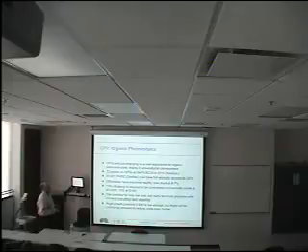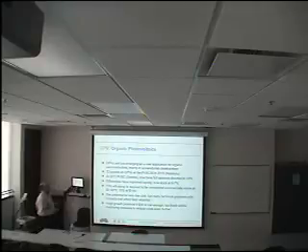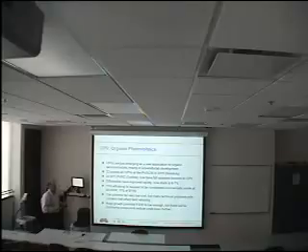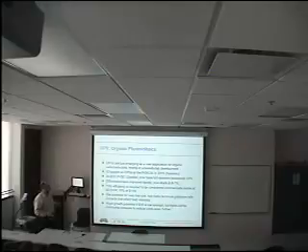Efficiencies have improved rapidly, though right now they're stuck around 6 or 7%. You need at least 10% efficiency to be commercially viable, and that's why they haven't taken off yet, at a cost of $0.50 per watt. If you could get the efficiency up to 15%, then the dollar per watt target is viable. However, the cost of silicon panels keeps going down, so this dollar per watt target is a moving target.